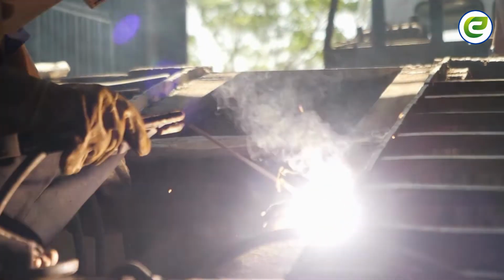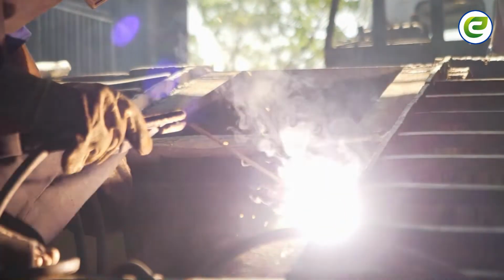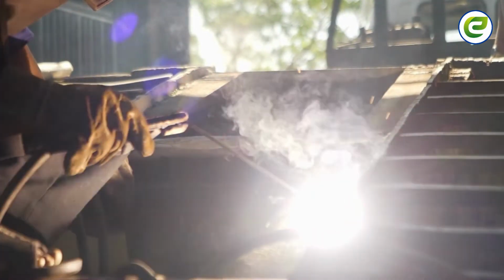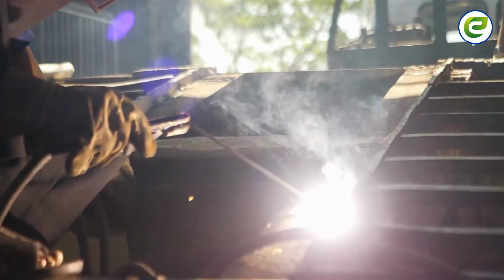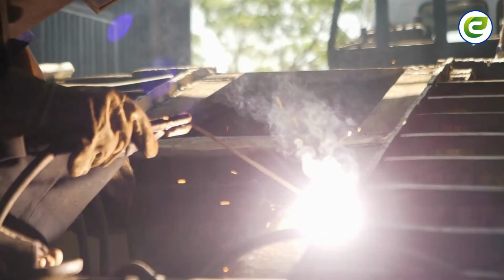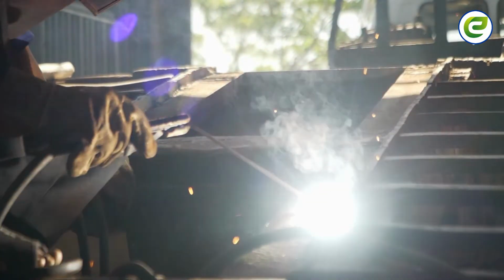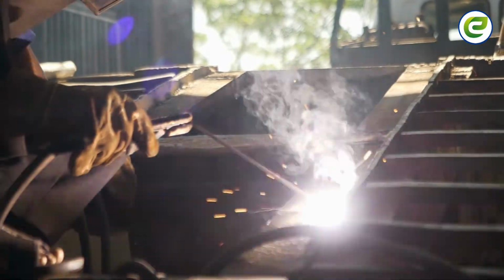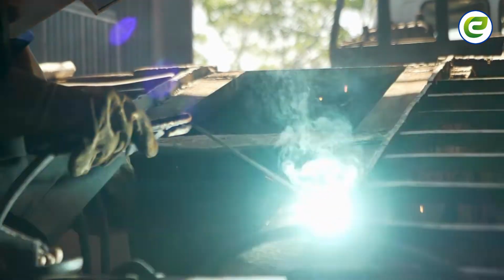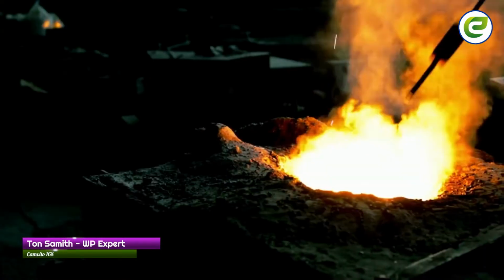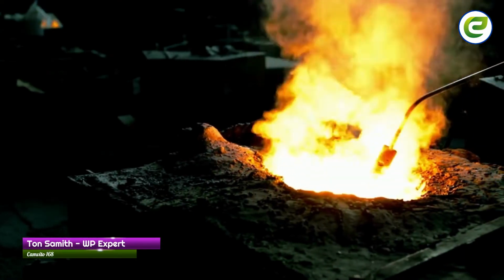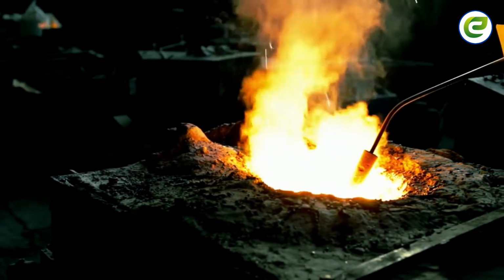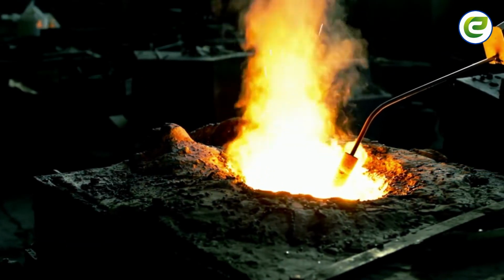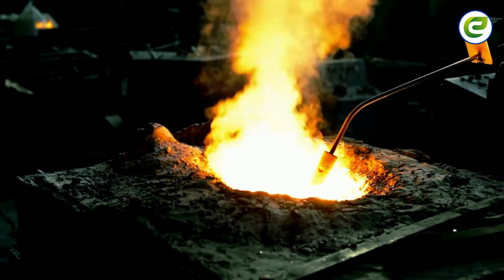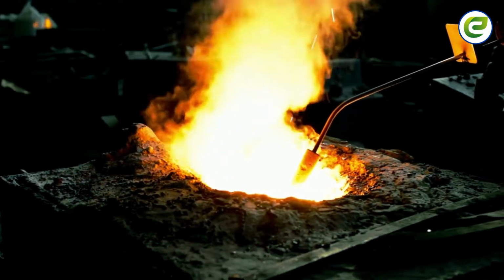Secondary steelmaking. With the need for improved properties in steels, an important development after World War II was the continuation of refining in the ladle after the steel had been tapped from the furnace. The initial developments, made during the period 1950 to 1960, were to stir the liquid in the ladle by blowing a stream of argon through it. This had the effect of reducing variations in the temperature and composition of the metal, allowing solid oxide inclusions to rise to the surface and become incorporated in the slag.